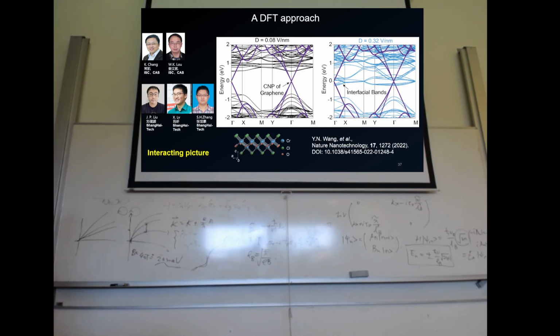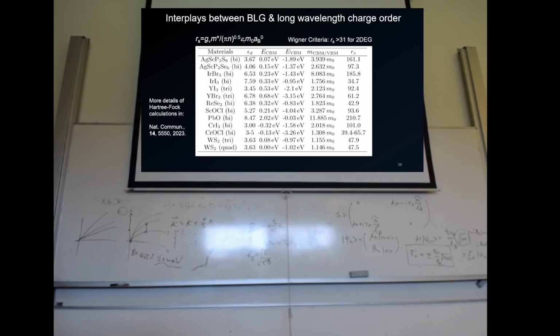So this is how we did. We have chosen an interfacial band, which, when you have the electrical field applied vertically, has a lower end of the interfacial band which is flat enough so that all the electrons, as long as you have electrons transferring from graphene into that surface band, they will form a kind of electronic crystal, and that's the picture. And indeed, by computing this RS value I just mentioned before, there were a bunch of systems in this table, and if you are interested, you can look into more details in the theoretical paper of this paper. There are a bunch of them that should show the same behavior, and 2 of them are already experimentally proven.